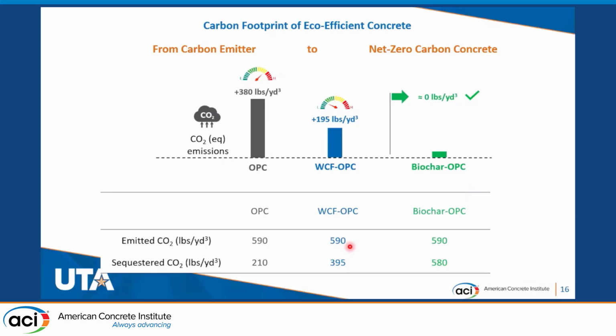We calculated the carbon footprint of this eco-efficient concrete, and it appears that the high carbon emission OPC can reduce the carbon footprint by using agricultural waste products. For example, the waste cellulose fiber concrete exhibits much lower CO2 emissions from around 195 pounds per cubic yard, while the addition of biochar in OPC results in a biochar OPC concrete with almost zero emissions. So we can safely claim a net zero carbon concrete.